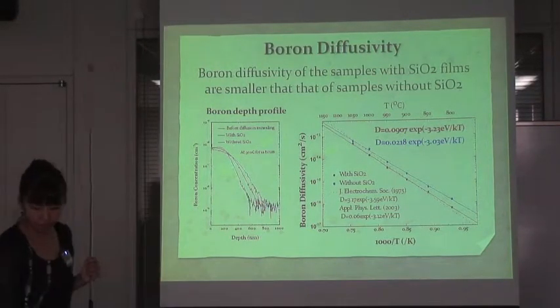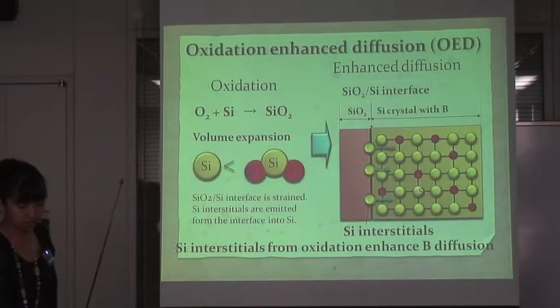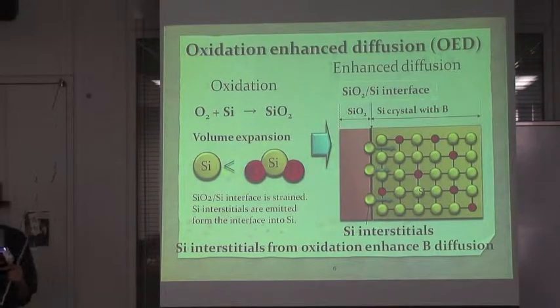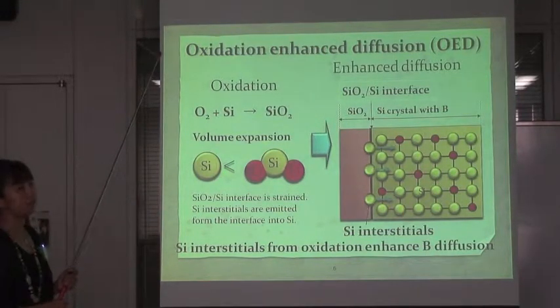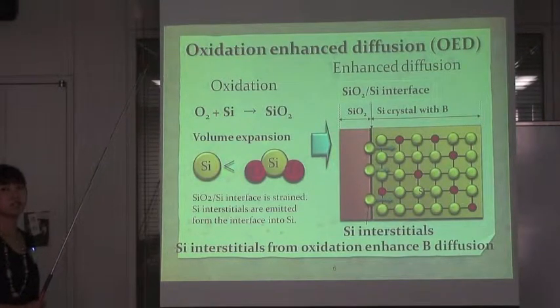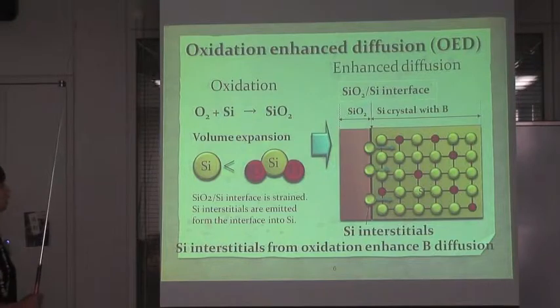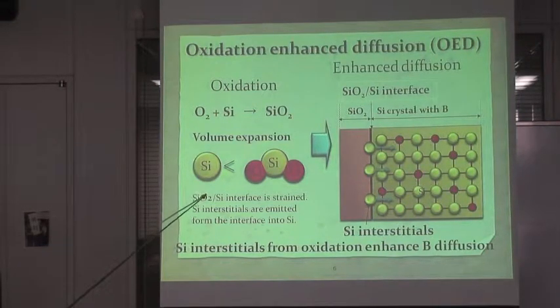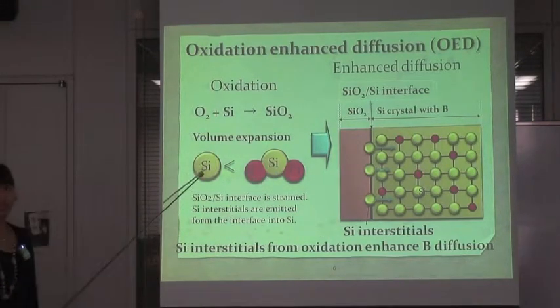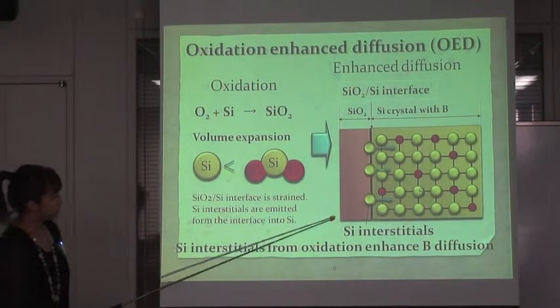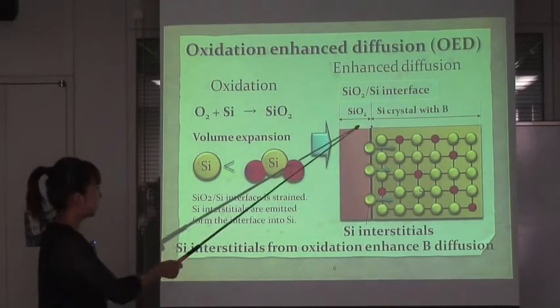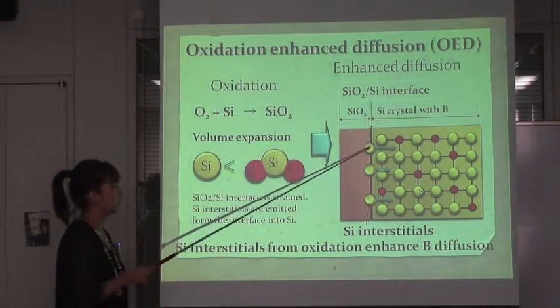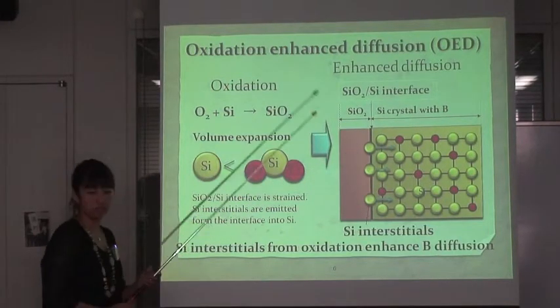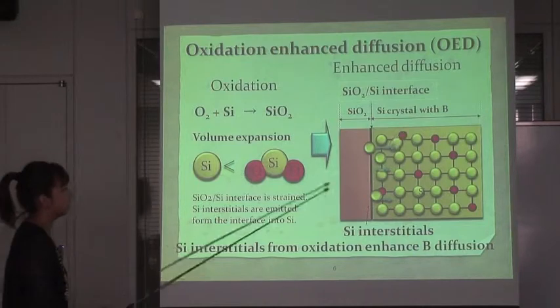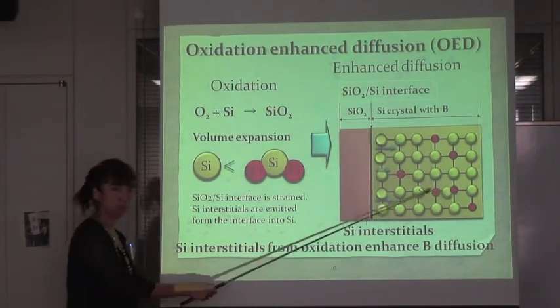Okay, I will explain why we have the difference. This can be explained by oxidation enhanced diffusion, or OED. So I will explain what OED is. When oxidation occurs on the silicon surface, the silicon dioxide silicon interface here is strained because the volume of silicon dioxide is larger than that of silicon. Therefore, excess silicon interstitials at the interface are generated and diffused into the silicon substrate. And these silicon interstitials enhance impurity diffusion.